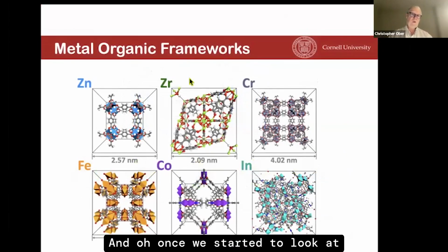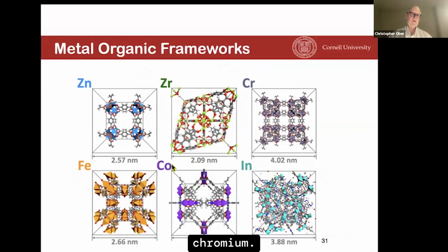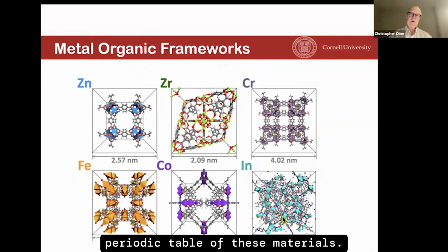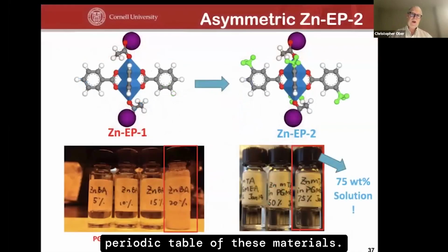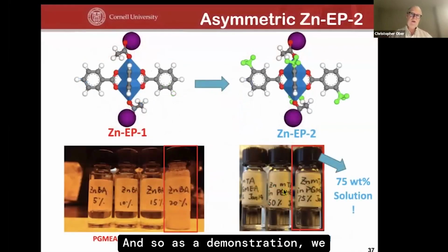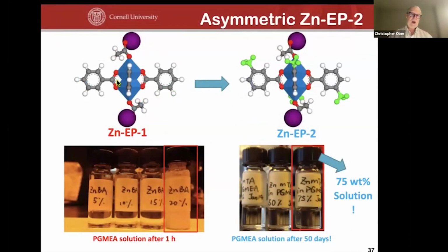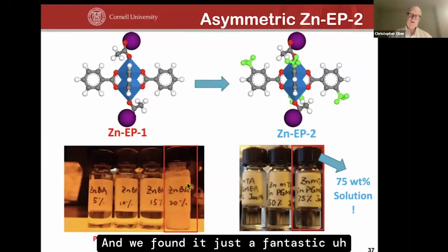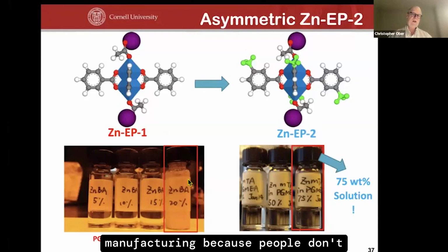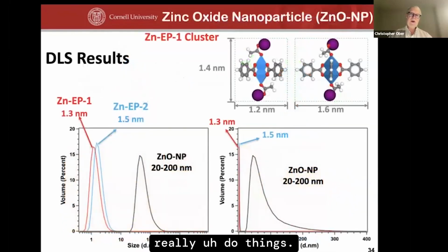And once we started to look at metal organic framework type of chemistry, we realized we could look at zinc and zirconium and chromium, indium. We could go through the periodic table of these materials. And so as a demonstration, we looked at zinc, and we found it's just a fantastic resist system that will never be in manufacturing because people don't like to put zinc on their device. But in terms of being able to pattern a material, you can really do things.